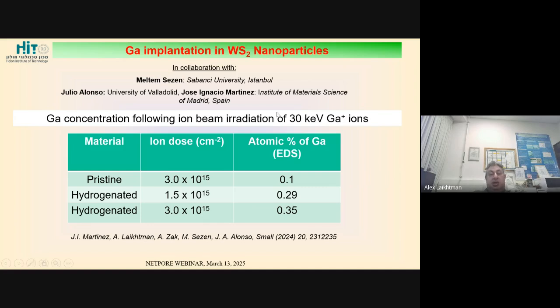It was quite interesting to us, and we did not have any explanation at that time, that in the case of pristine nanotubes, the atomic concentration of gallium was at the limit of detection, just 0.1 atomic percent, at an ion dose that did not produce any substantial damage to the nanotubes. Because if we increase the ion dose, then we have heating and melting of the nanotubes, so it's not good. We should maintain the ion dose quite low to keep the nanotubes in their pristine structure.